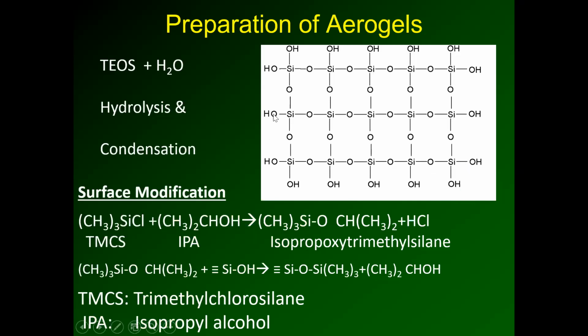You can see that the inner oxygens are neutral, but the outermost oxygens are unsaturated. So they are hydrophilic. They react and absorb the moisture, water, and become watery. So what we do is surface modification. We did it with trimethyl chlorosilane, TMCS. When we take this, it turns the hydrophilic nature into hydrophobic, and it will be so forever actually.